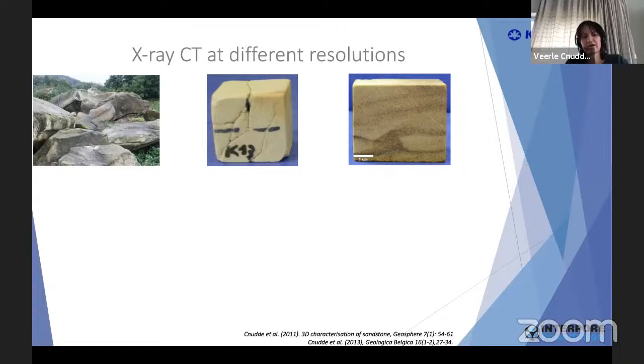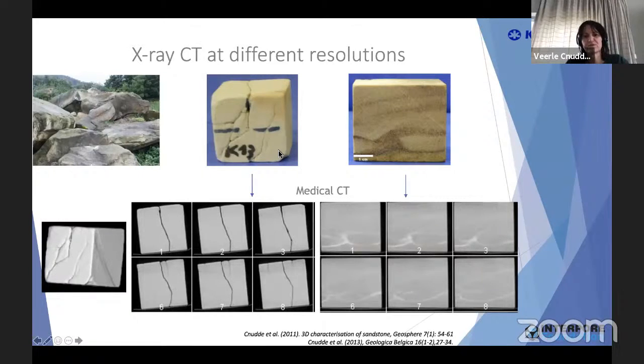But if you would scan this in a medical scanner, and these are blocks of 5 by 5 centimeters in size, you can immediately virtually cut this open and see the different fractures. You also see the different layers because there is a contrast between the quartz rich zones and the iron richer layers, which have higher attenuation for X-rays and are therefore brighter. So you can virtually cut it open and look at the internal structure of your rock.